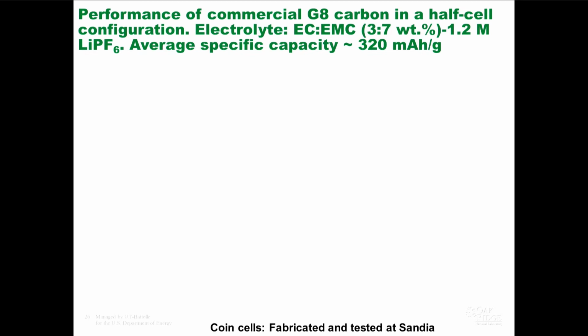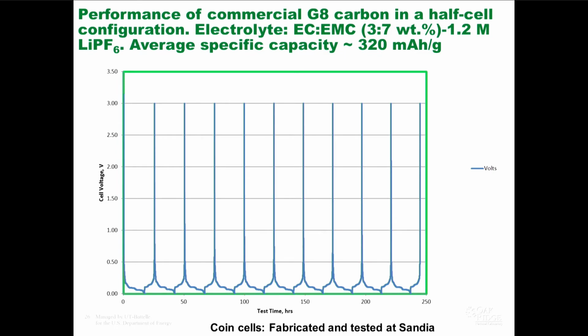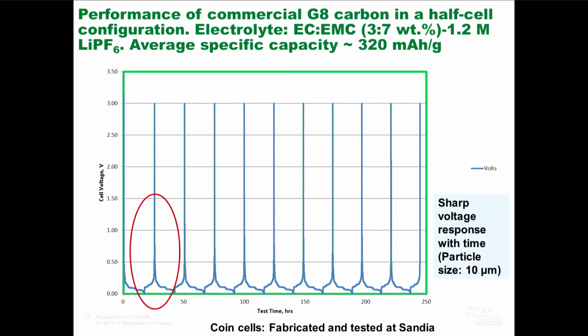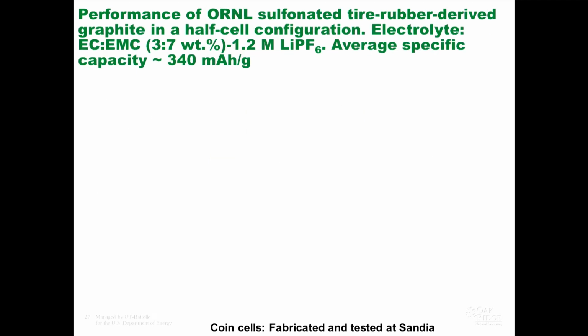So what they did was they took their standard commercial G8 carbon with a capacity, and they achieved. So we have plotted voltage versus time, and one good thing is the capacity is 320 milliamp hour per gram, but sharp voltage response with time. One thing I heard is these commercial graphites have particle size like 10 microns, really uniform, and this is a commercial sample. Let's see how the ORNL sulfonated tire rubber derived graphite performed. And this is again in a half cell configuration, and they achieved 340.